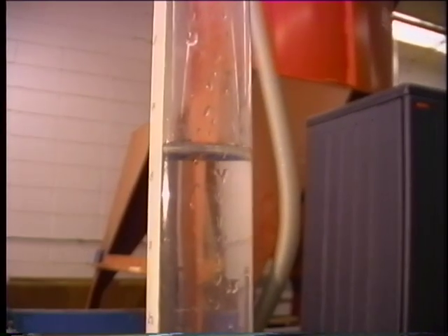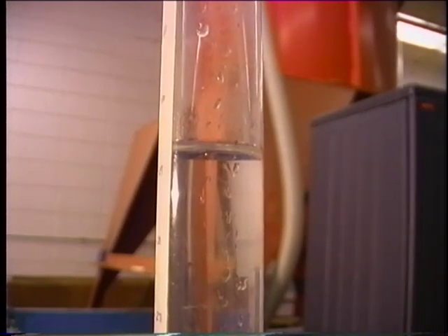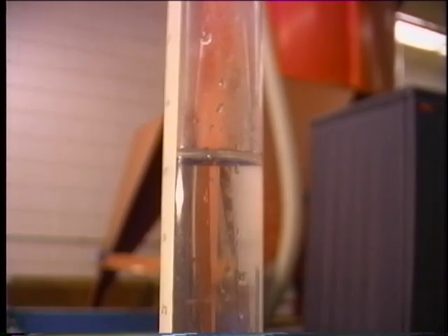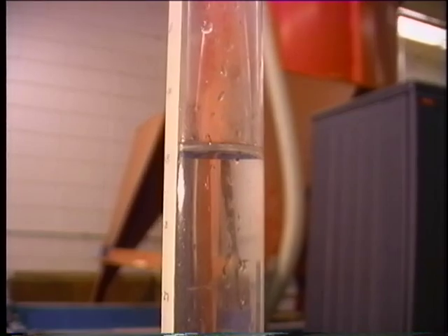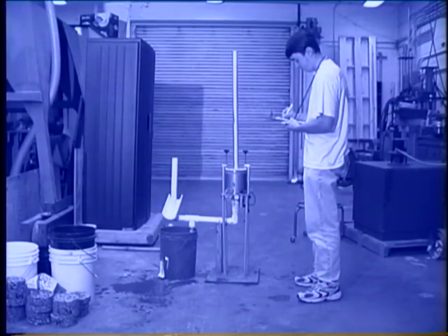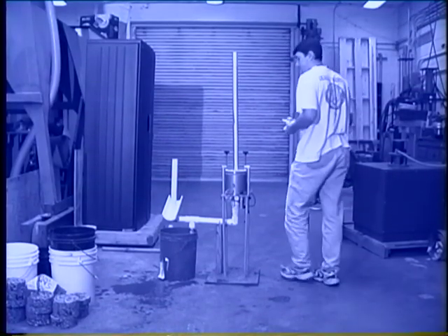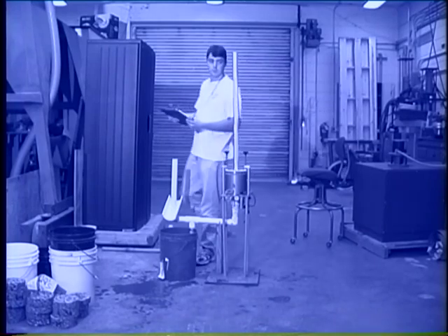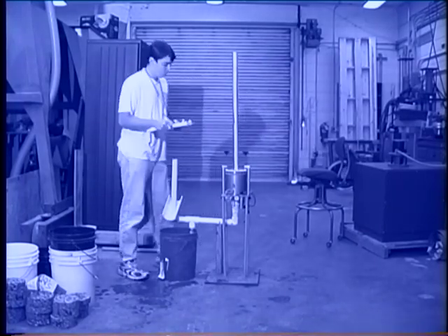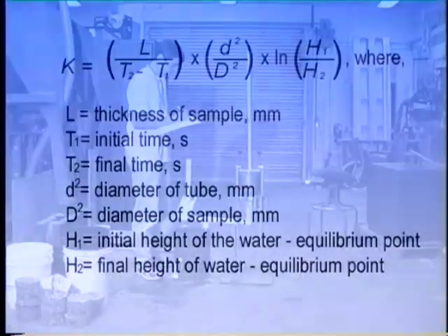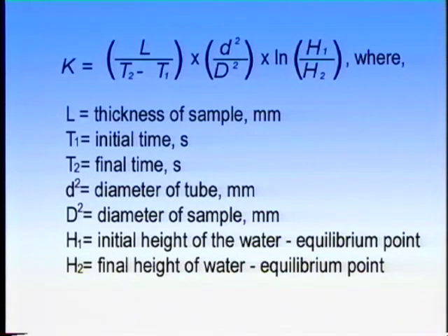The test is finished when the water falls to 3 inches above the equilibrium point, which for this apparatus is the 8-inch mark, or when 2 hours have passed. The test cannot end below the 8-inch mark because the amount of error in the equation to find the K value will be too great. The coefficient of permeability is the K value. The K value is the distance water will travel through the asphalt in a given amount of time.